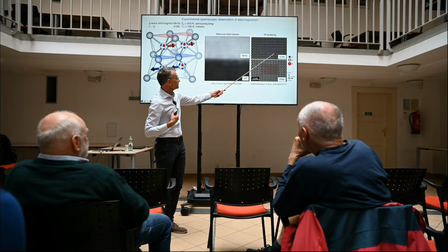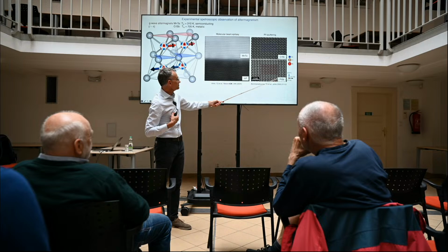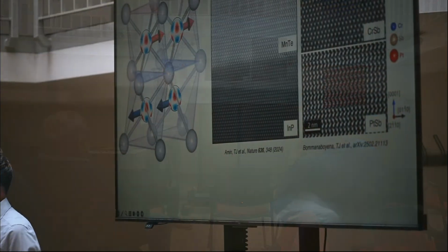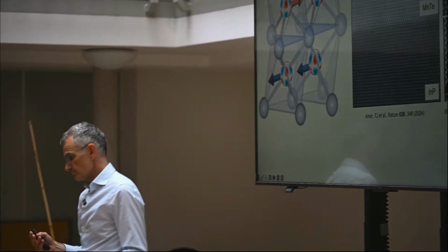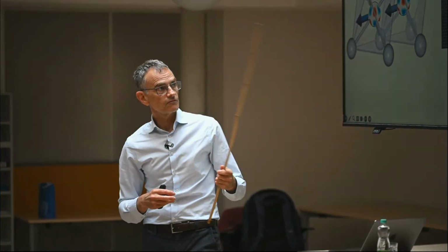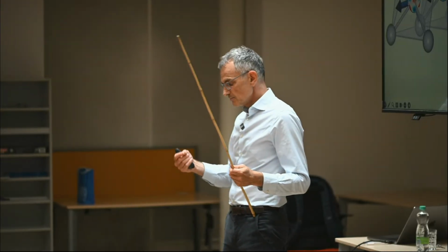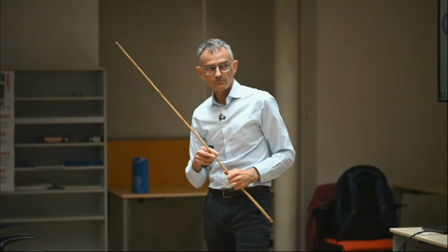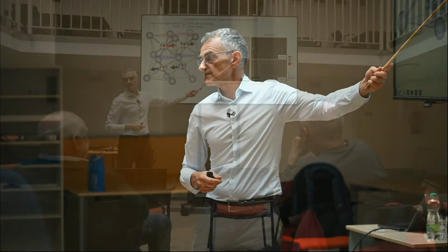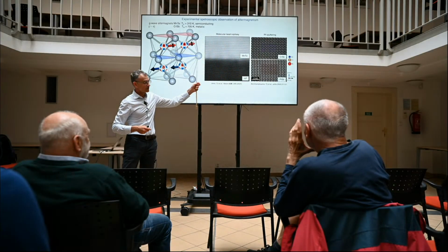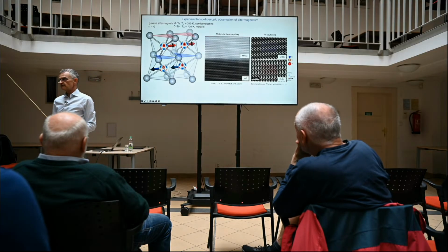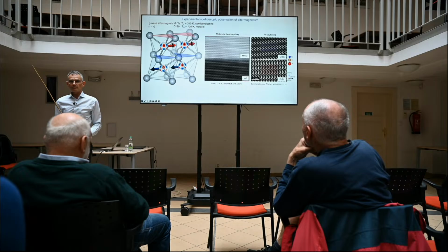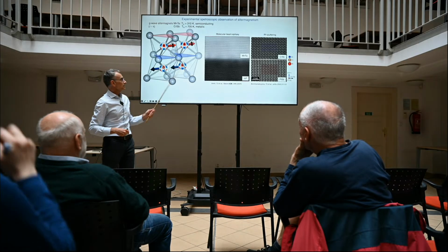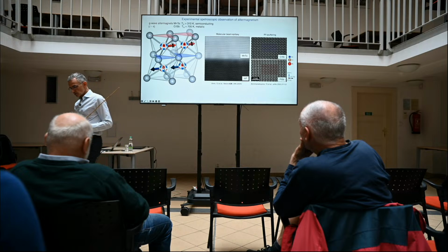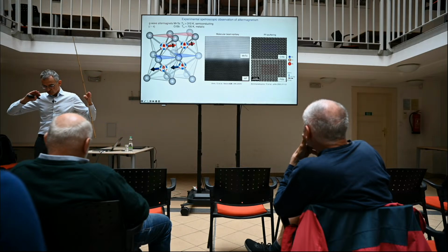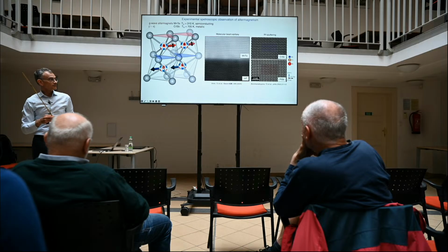This is the chromium antimony altermagnet grown on top of a platinum antimony substrate by magnetron sputtering. This is RF sputtering, which typically is a rougher method for thin film synthesis, but it's very important because it's the industrial method, which is also used for MRAMs. The same thing: the chromium antimony across the entire wafer, of a thickness of tens of nanometers, is virtually defect-free. So we have methods to prepare extremely high quality materials, which is the starting point for doing experiments and getting rid of all possible artifacts, obviously.